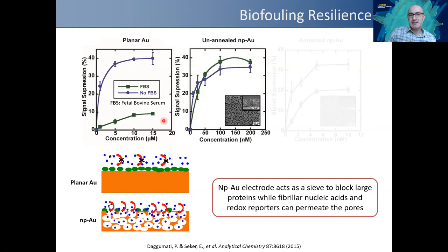Nanoporous gold surprisingly really prevents this, and there have been a few other groups that looked into this in the context of electrochemical performance. What happens is that even in phosphate buffer or in serum, the effect is really not lost. You can still detect with high fidelity. And the reason for this is that the nanoporous gold acts as an intrinsic sieve where the large molecules are excluded. But since the pores are irregular, they are not completely occluded by these proteins.